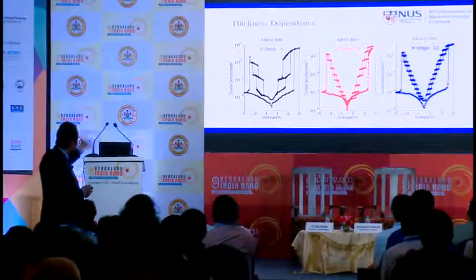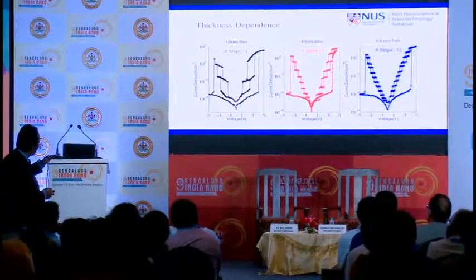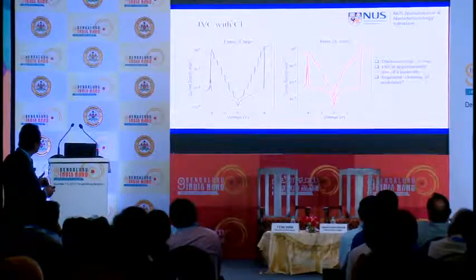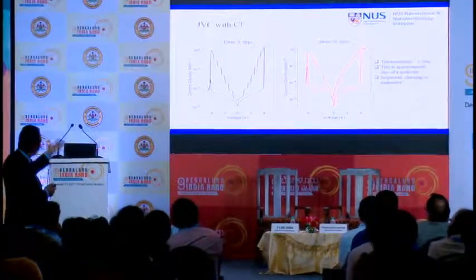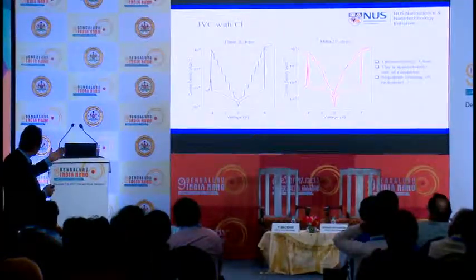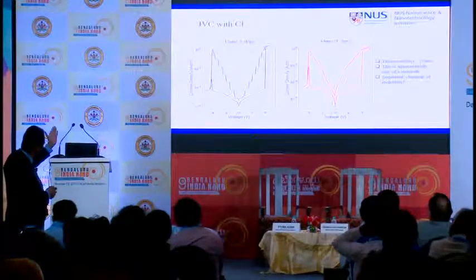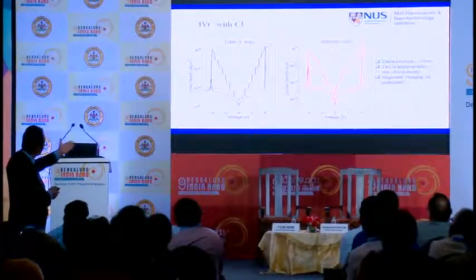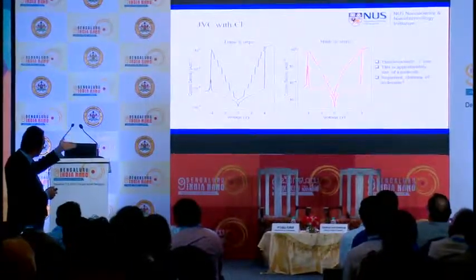The quantum of 3 units also switching. And this has to do with the counter ion. So we said if you make the counter ion lighter, then when one layer switches, the other layers may not feel it. And so we went to a chlorine counter ion, which is a low energy, much smaller thing. And now you can see a 12 nanometer film produces 8 steps, and a 44 nanometer film produces 29 steps.